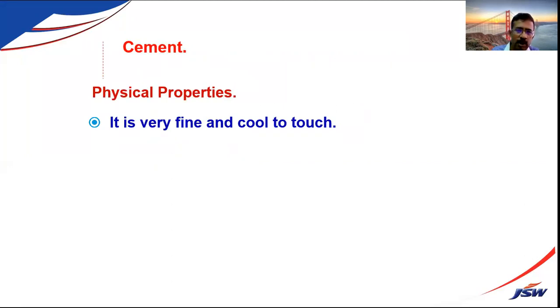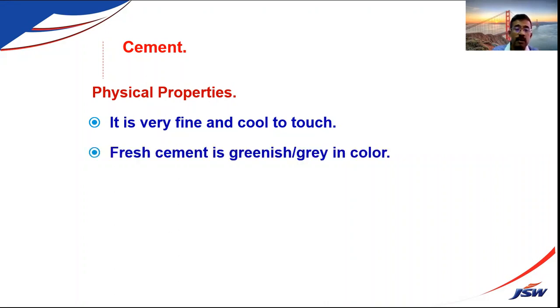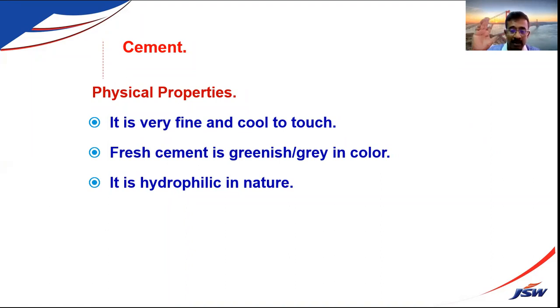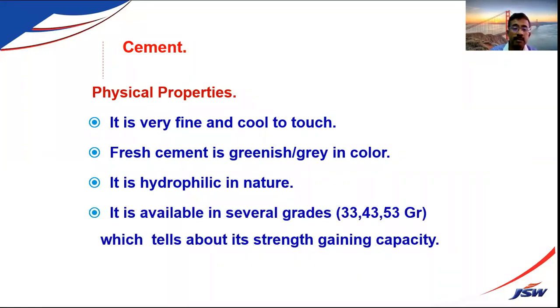If you're using cement, you should always get fresh cement. You can use cement up to 1 or 2 months old, but it should be properly stored, then only that cement will be good. It is hygroscopic in nature, so it absorbs moisture. So it should be watertight. You should store it in moisture-tight godowns. Proper packing of the godowns is very important. Otherwise, in the rainy season, the cement gets damaged if you are storing it for a longer time.